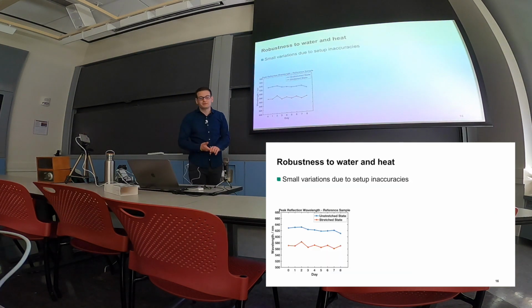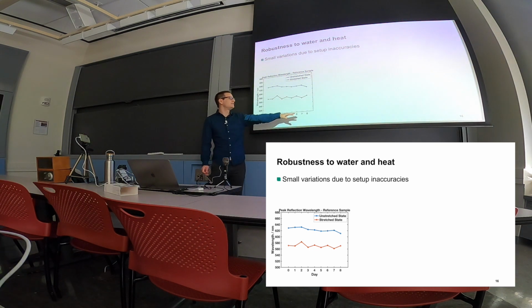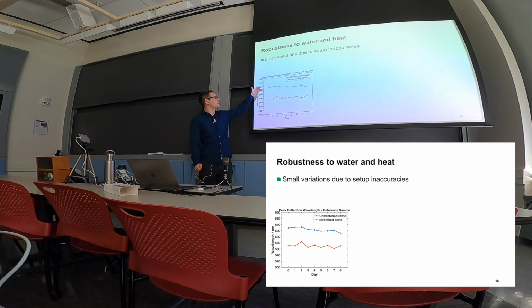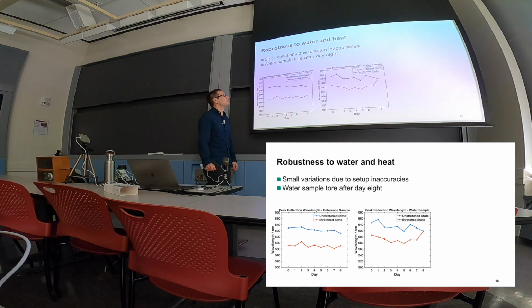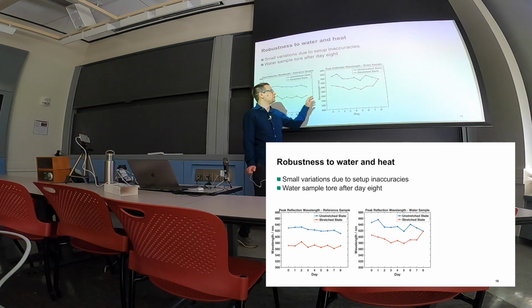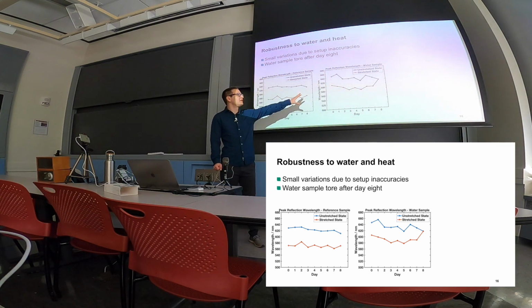And the results have been that for the reference sample, of course, there should not have been anything happening after the first measurement that I've also done, and this is also what came out here. So over a course of 8 days, the peak wavelengths in the unstretched and stretched state stayed quite constant. There are some variations that come from setup inaccuracies, because I needed to get the sample out of the measurement system and back in after each day. But that is a quite good result. Then the same for the water sample, being in floating water. Also here no aging can be observed, also just some setup inaccuracies.